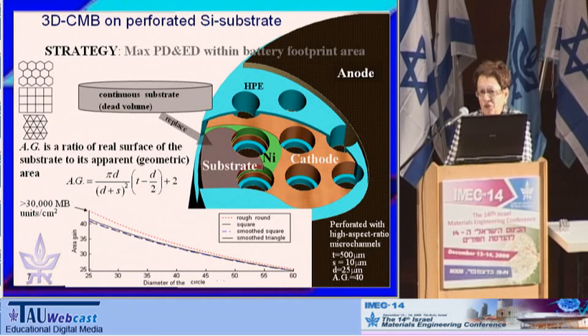The most obvious approach to achieve a significant geometrical area gain is to replace the continuous substrate by a perforated one with high aspect ratio microchannels. The three-dimensional thin-film concentric microbattery, which is currently under development in our group, has a typical sandwich-like battery structure with successive layers of current collector, here it is, cathode, hybrid polymer electrolyte membrane, and anode.